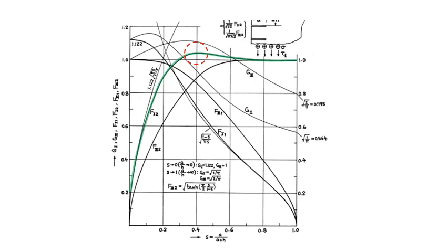Now you'll see that the green line that defines what we're looking at essentially shows how the stress intensity factor is going to change as our spacing parameter changes. And when you look at the way that they've manipulated it, it basically says that if you have a constant crack spacing, which of course we will have, going from left to right on the plot basically describes what's going to happen to our stress intensity factor as a crack propagates, or in fact, as all of those cracks propagate.